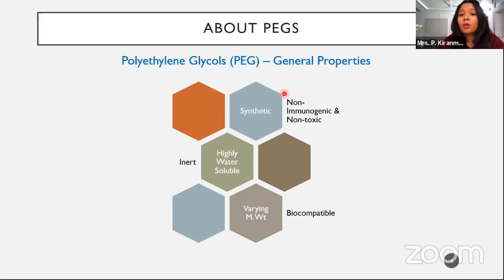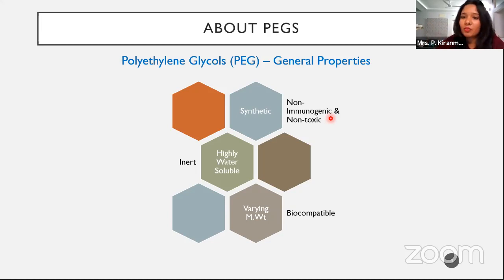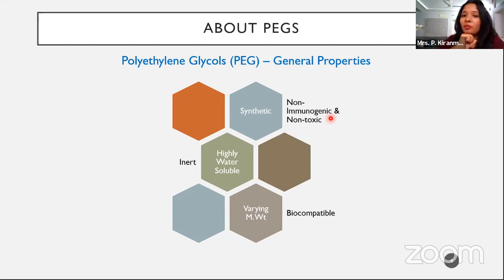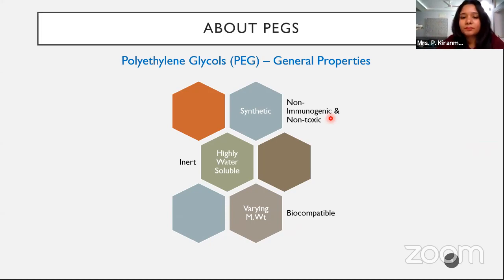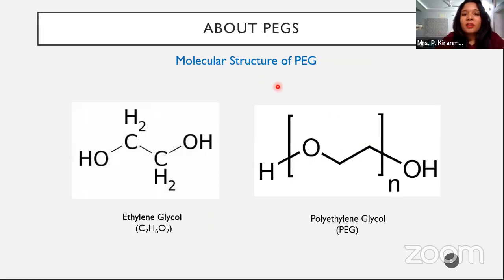Most importantly, when combining a PEG molecule with a protein, the most prominent advantage is that it is non-immunogenic — it can make the protein non-immunogenic as well. This is of very high importance in clinical trials. Whenever a protein is administered to the body, it causes immunogenic reactions, phagocytosis happens, and the efficacy of the molecule is reduced. By introducing PEG to the molecule, the PEG surrounds the protein, reducing its immunogenic properties, resulting in longer half-life, longer circulating time, and increased efficacy.